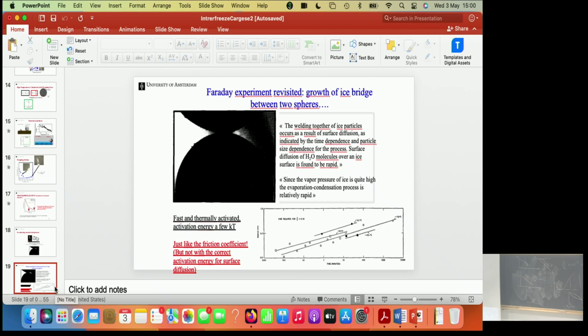So this is very nice, because it goes with everything that I've told you so far. The only problem is that if he tries to get the activation energy from his surface diffusion measurement at different temperatures, it's hard for you to read probably, but at low temperatures the neck growth actually goes much slower than at high temperatures. So this is radius as a function of time. And so if you plot the rate as a function of the inverse temperature, you get the activation energy.